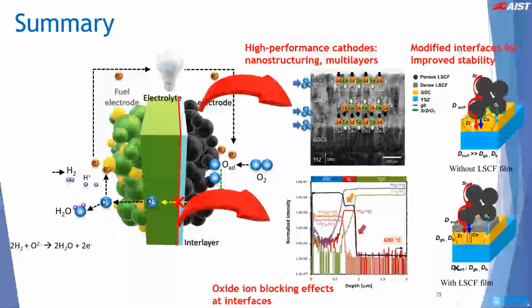Lastly, with the goal of mitigating the effect of strontium zirconate on long-term degradation, we devised a way to improve the stability of the interfaces via introduction of an additional dense LSCF layer, which in conjunction with a dense GDC layer, helped to further reduce cation interdiffusion in the cell. With this modification, we were able to improve the degradation rate with long-term testing and achieve better stability of the polarization resistance with time. For each of these investigations, I hope I have shown that SIMS as an analytical tool plays a major role in our development of materials for high-performance SOFCs.